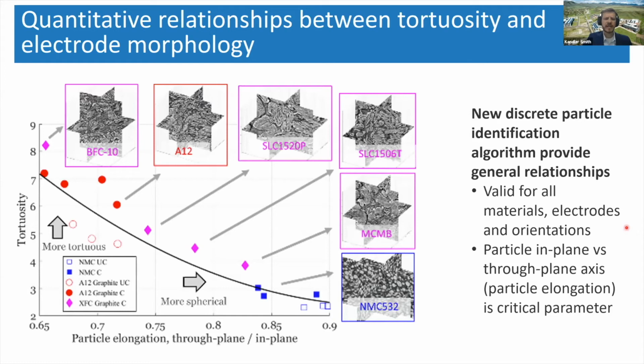But with that, one of the key metrics that he came across to help correlate with tortuosity, and this seems to work across all these different materials. Here we've got 1 NMC material as well as 5 different graphite materials. Basically, the sphericity is very important, but if the particle is not spherical, the metric that he's come up with is particle elongation in the through plane direction versus the in plane direction. So you can imagine if you have platelet-like particles which are aligned in plane, then you're on this part of the axis. If you have platelet-like particles that are stood up straight, then you're off this axis to the right side here and have very low tortuosity. And so with this, he's come up with very good correlations that describe for any arbitrary material a prediction of the tortuosity.